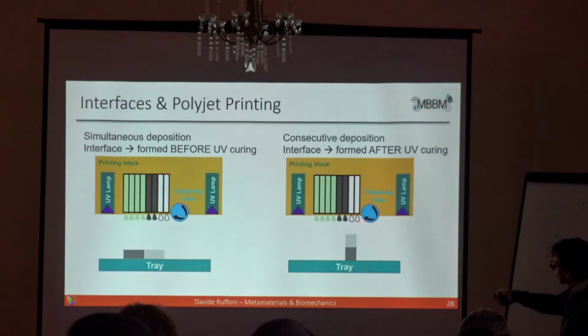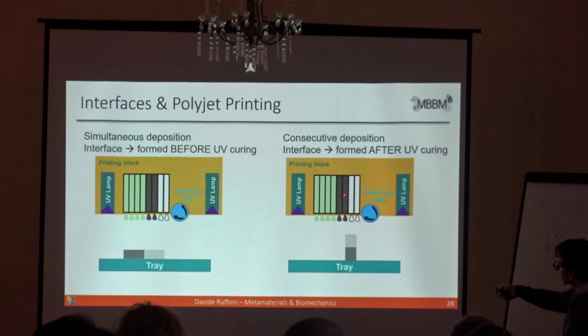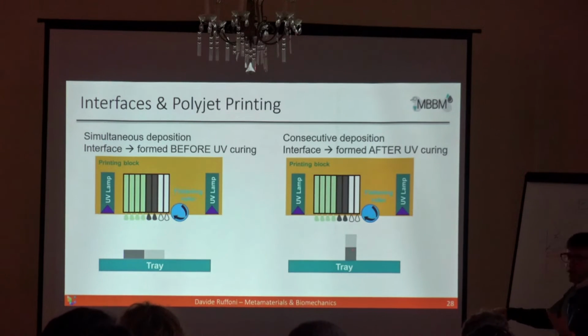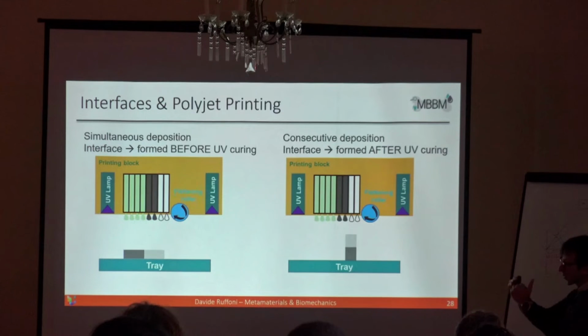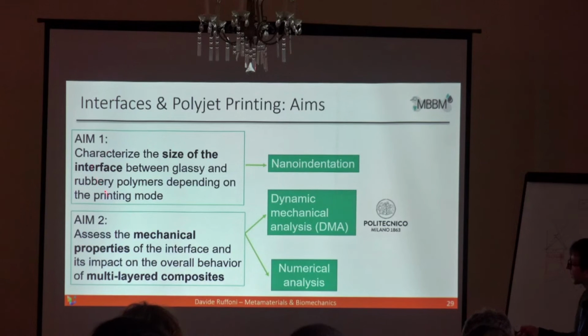Otherwise, if you print the object oriented vertically, so to say, you are depositing the second material on a surface of a structure which is at least already partially cured. So this interface between the two voxels is formed after at least partial UV curing. We are interested in the properties. The research question here is: are there different properties? Is the interface different in these different situations? And what are the properties of the interface? And more in general, if I have a very simple composite material of soft and stiff voxels, what is the role of the interface in the mechanical behavior of those composites?